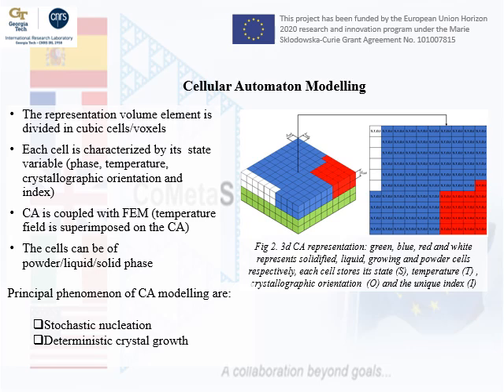Okay. Now, once we have discretized the volume which we are interested in simulating, we also need to apply a temperature field, right? This is important because in the case of additive manufacturing, we have a very high heat source, like the laser, and for that reason, to be able to impose the temperature field on the microstructure field of the cellular automaton itself, we need to perform an additional simulation, right? The temperature would be almost impossible to determine experimentally, right? Because we would require knowing the temperature at different positions of the representative volume element, and there are no instruments that can measure the temperature field with that high localized accuracy, for example, right?